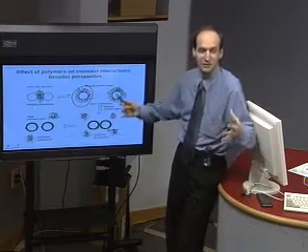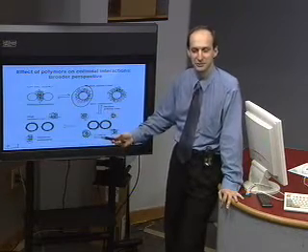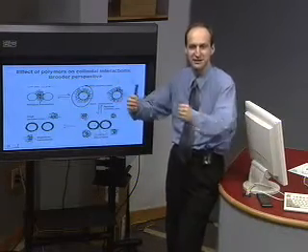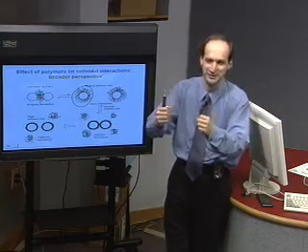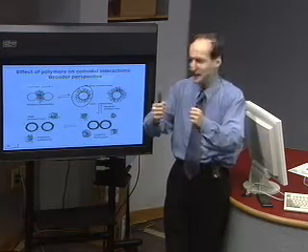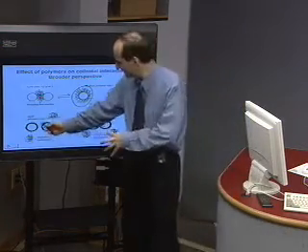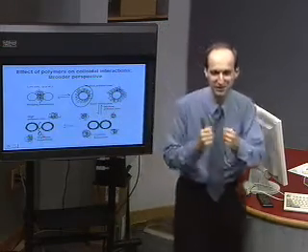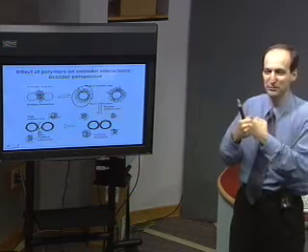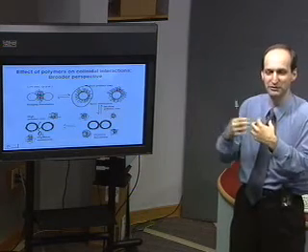When you put more polymer, there is no place on the particle where it can go, so it just stays in these globules with a radius of gyration, which act in this case as small particles which bring the large particles together by depletion forces. And if you put so much polymer that everything is filled with polymer, the particles are not going to stick, because they cannot push the polymer out of the way, and they repel all the molecules in the middle.